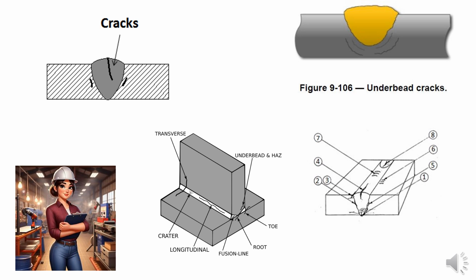Hydrogen and cold cracking, the dynamic duo. Now let's talk about the hydrogen that causes the cold cracking. It's like a sneaky little troublemaker that, when trapped in your weld, makes it a lot more likely to crack later on. Hydrogen comes from all over: moisture in the electrode, flux, or even just the air around the joint. Here's the kicker. Hydrogen-induced cracking doesn't happen instantly. It waits for the right moment. When the weld metal is cooling, when there's tensile stress on it, and when the steel is in a brittle state. That's when it causes the big problems.